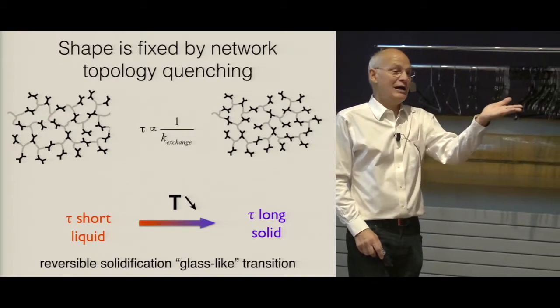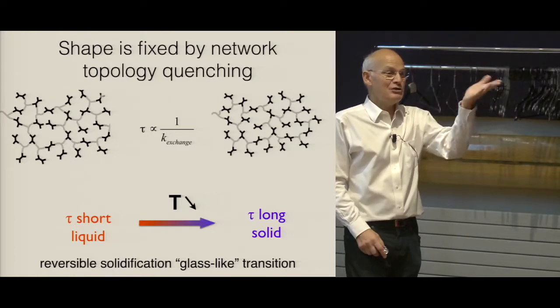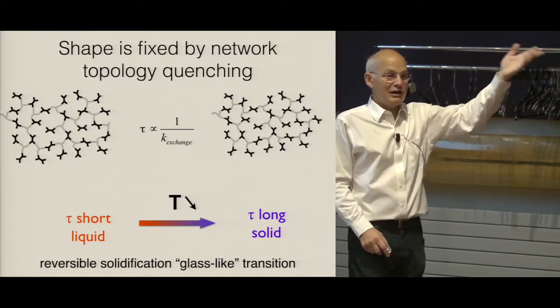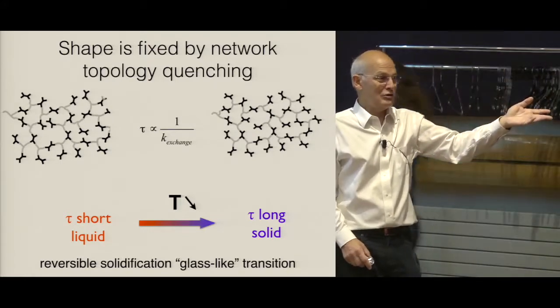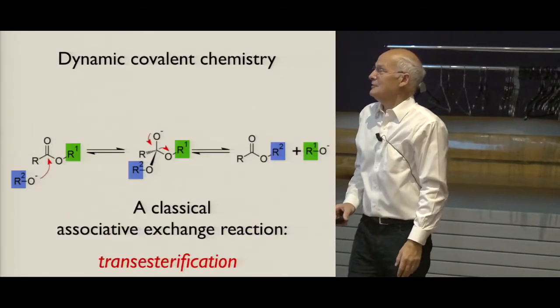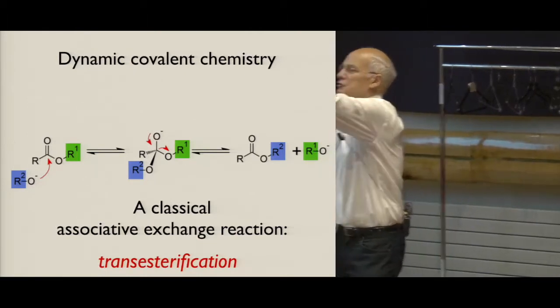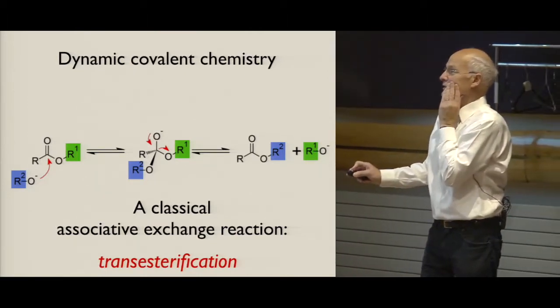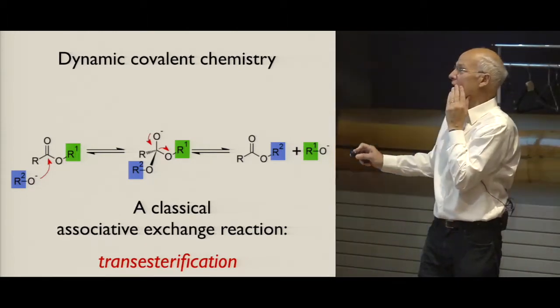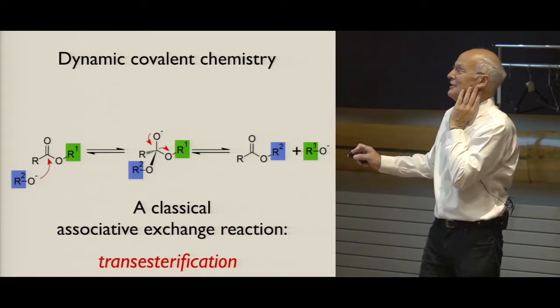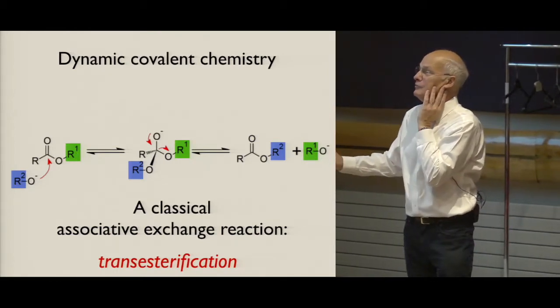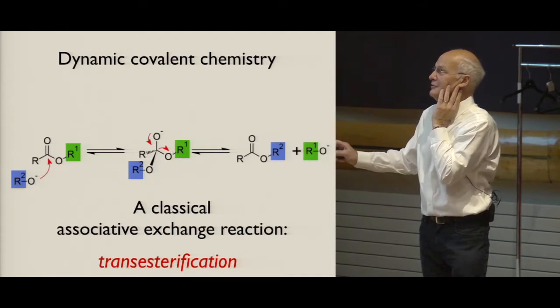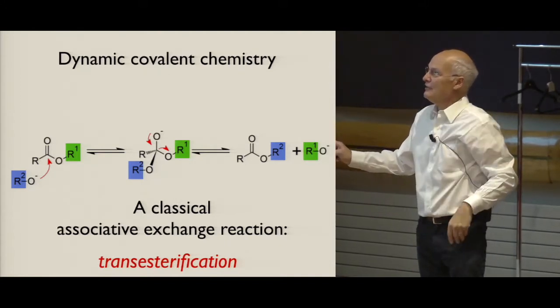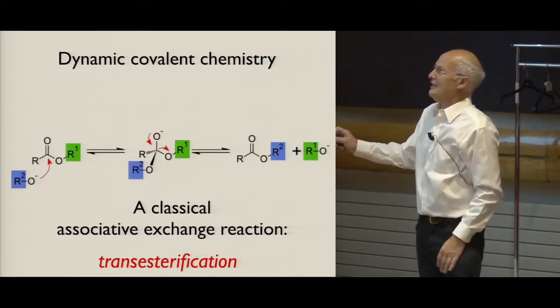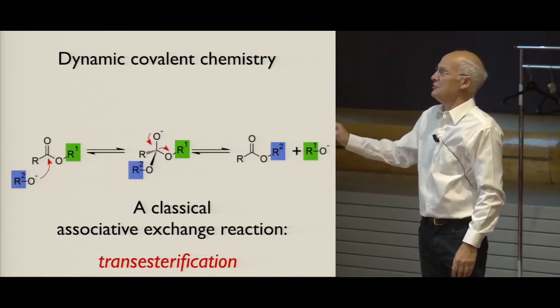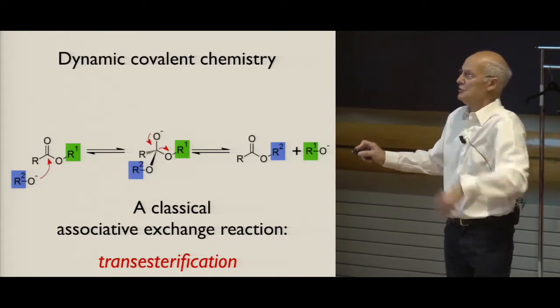And so if the reaction is thermoactivated, this means that the system will change the relaxation time by a simple Arrhenius law. Okay? And so the first reaction that we used is transesterification, which is used all the time in the industry. You take an ester, you make a pyramid, and then you exchange the radicals here. It's exactly what we did.